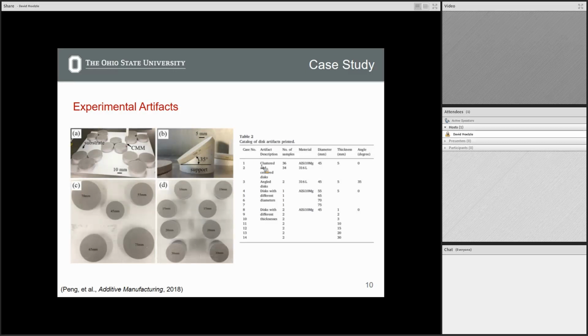So we looked at, I don't know what the number is, the number of samples we actually printed. It's quite a few, close to 100 parts that we printed for this study. And each of these was also characterized, which takes a lot of time. So this was essentially a graduate student and a postdoc, about a year and a half of their life making samples and characterizing them, somewhere in that range. They were doing other things too.